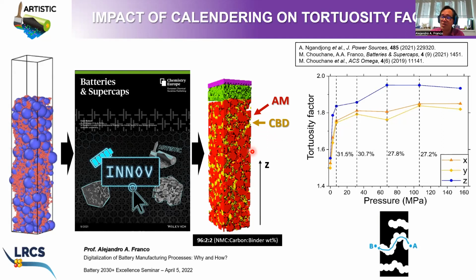In this case, we use TauFactor, which is a software developed at Imperial College using MATLAB. And then we can evaluate the impact of the applied pressure on the tortuosity factor along the Z direction, which is the thickness of the electrode, right? But also we can evaluate the impact of the calendering pressure on the tortuosity factor across the plane, across X and Y. So what we observe here, as expected, also from an experimental point of view, is that when you increase the calendering pressure, the tortuosity factor increases. But then at some point it reaches a plateau, because then it's not possible anymore to calendar the electrode, except if you crack the particles, right, in that situation. So this is very interesting, as you will see later on, because if you have electrodes that have been calendered a lot, you will have high tortuosity factors, and therefore for the electrolyte wettability, you will have more troubles, right?